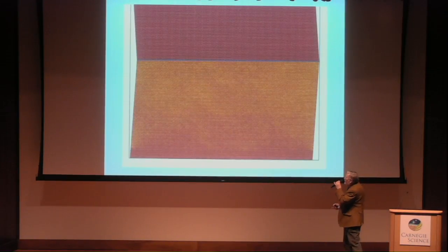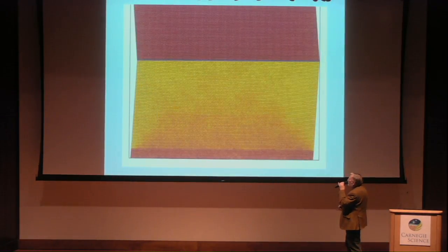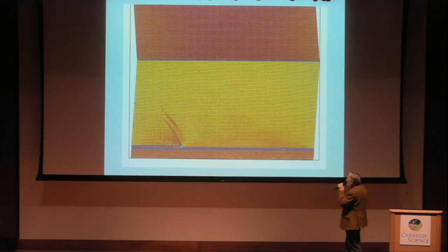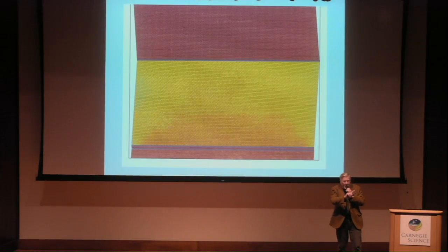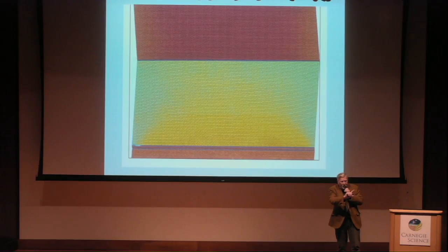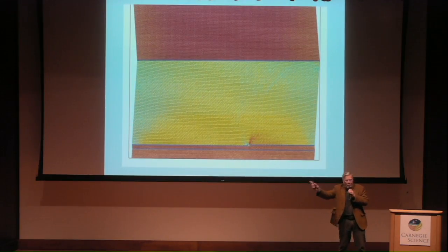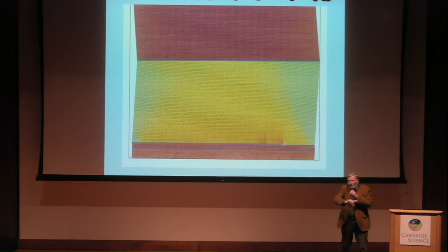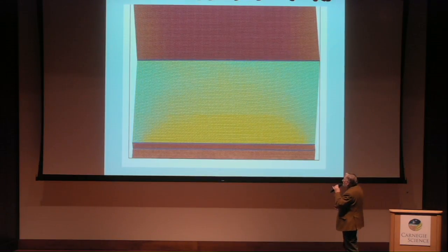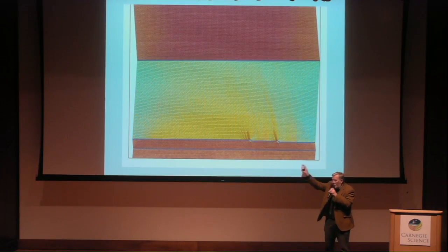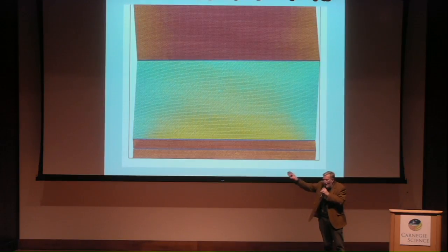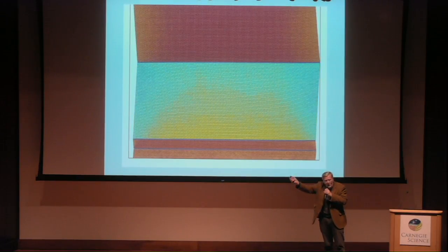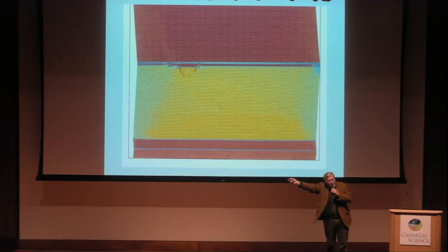So here I want to show you how that happens in a computer simulation. Now going back to the kink, which is our best example. So we stabilize this one, we destabilize this one, and we do it by what we call zipping. It's like needlework, right? There's a kink going forwards and backwards and forwards and backwards, weaving the new phase in. Now what is interesting, of course it happens in a statistical way, is this phonon branch which comes out. When they go, of course, they lose some energy. It's not very much, but they lose a little bit of energy, and the phonon branch goes backwards.